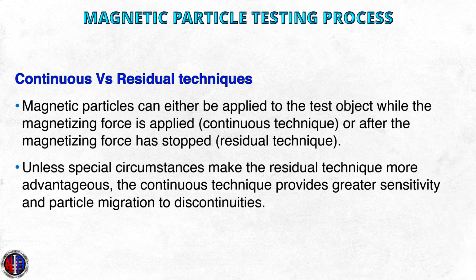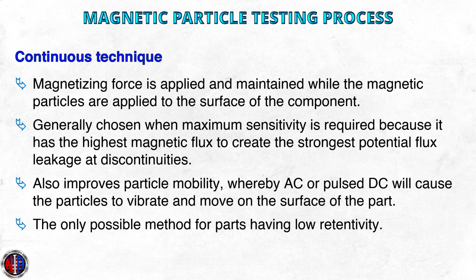Continuous versus residual techniques. Magnetic particles can be applied to the test object while the magnetizing force is applied, meaning the continuous technique, or after the magnetizing force is stopped, the residual technique. Unless special circumstances make the residual technique more advantageous, the continuous technique provides greater sensitivity and particle migration to discontinuities. Continuous technique. Continuous magnetization describes the technique where the magnetizing force is applied and maintained while the magnetic particles are dusted for dry particles or flowed for wet particles onto the surface of the component.